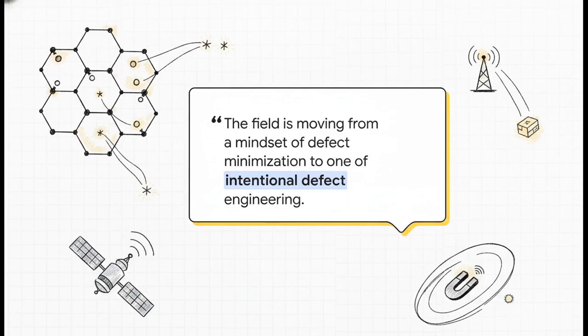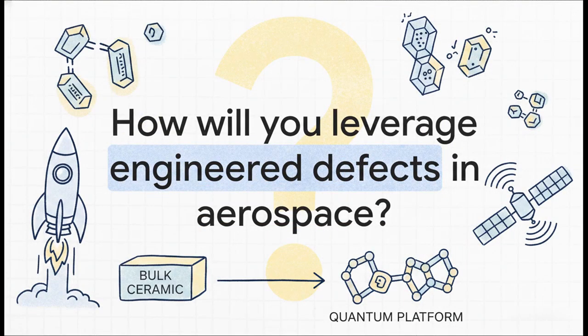Historically, material science has always been about eliminating imperfections, right? Well, now we're purposely knocking out nitrogen atoms or adding carbon atoms to the lattice. Why? Because these specific engineered defects act as stable, room-temperature single-photon emitters. This completely transforms HBN from a bulk refractory ceramic into a customizable, functional platform for next-generation quantum communications and ultra-sensitive magnetic sensors.